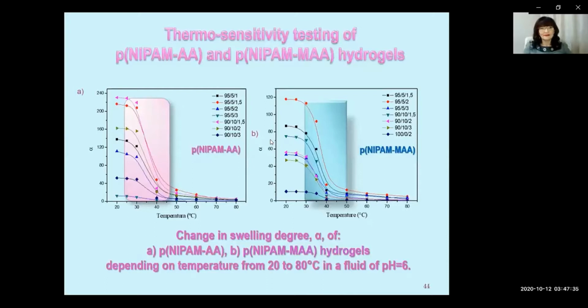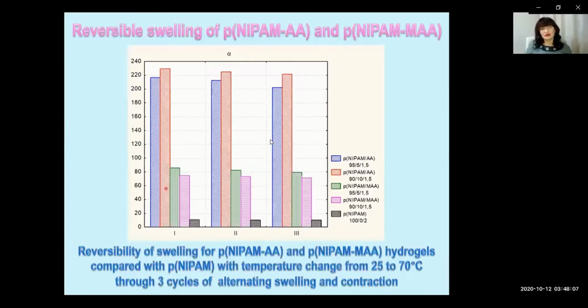Thermosensitivity testing of synthesized hydrogels showed the volume phase transition from 30 to 45 centigrade as a result of breakage of bonds between the polymer chains and water, which causes contraction of the hydrogels and water release. Reversibility of swelling of obtained hydrogels followed the trend of decreasing swelling during the process of heating and cooling.